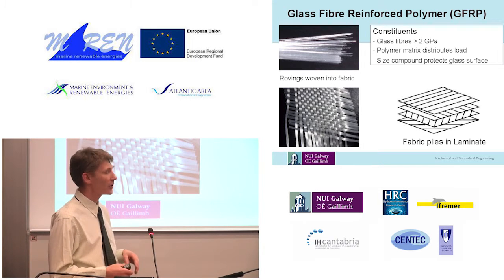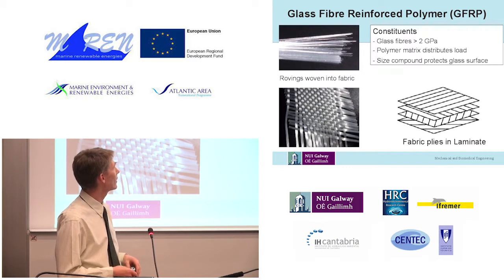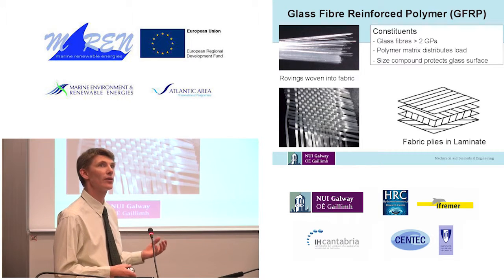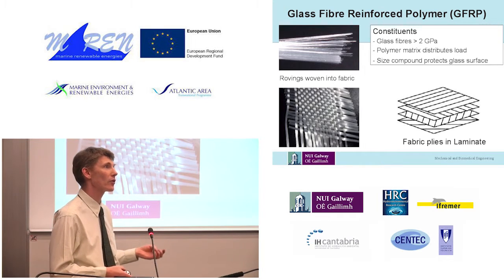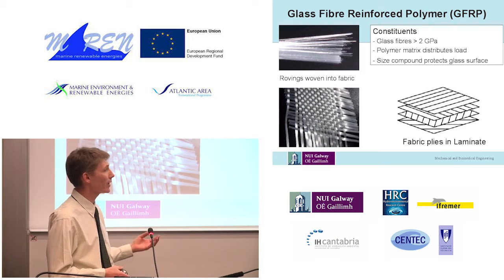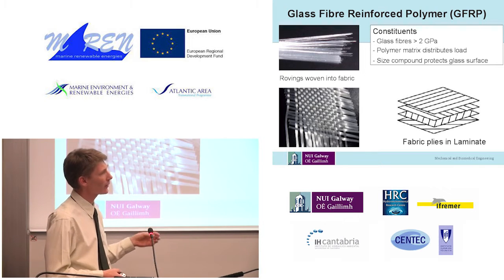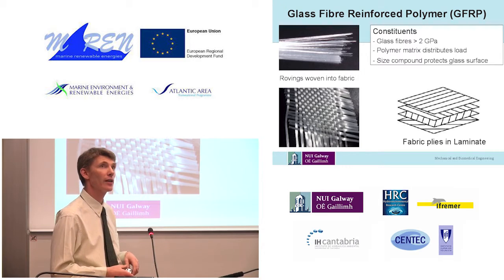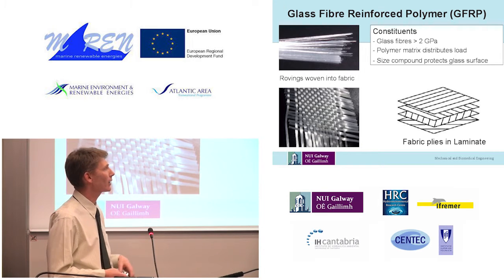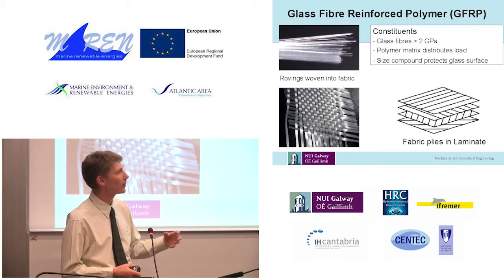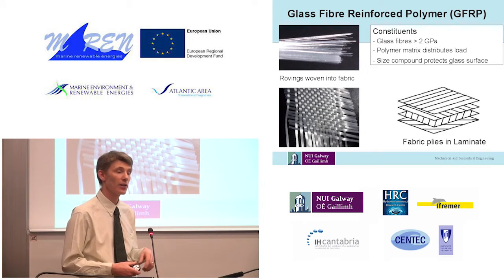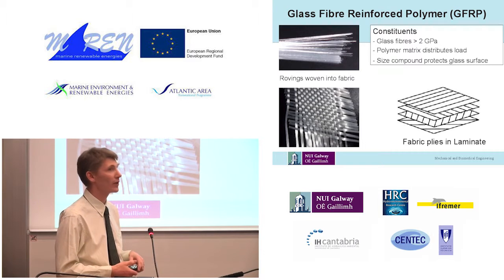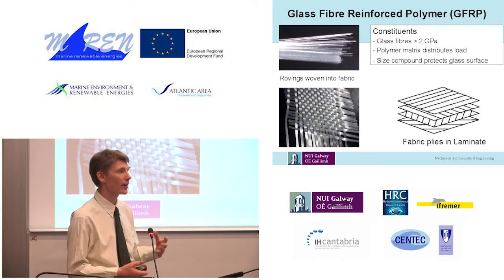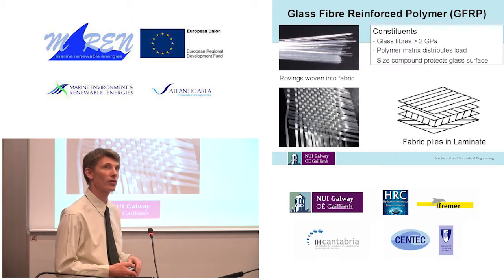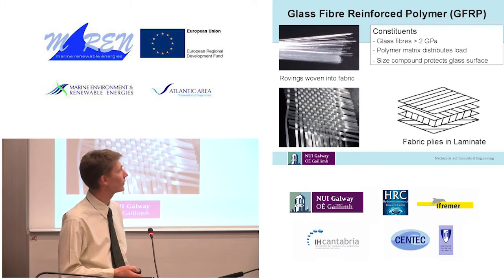And then the other material that kind of gets forgotten that's in there is a size compound that's applied to the fibres as they're drawn, and this size protects the glass fibres during processing, and it also has a silane molecule in there that helps to bond the polymer onto the glass surface, and it protects the glass surface from the effects of moisture. If you don't have that, the moisture tends to cause stress corrosion cracking of the glass fibres.